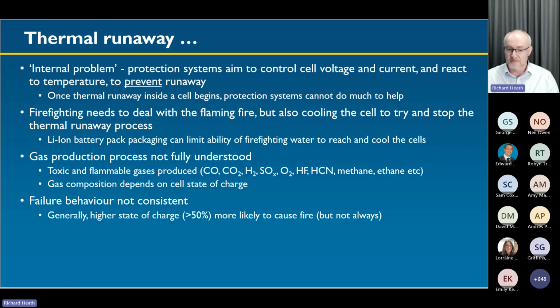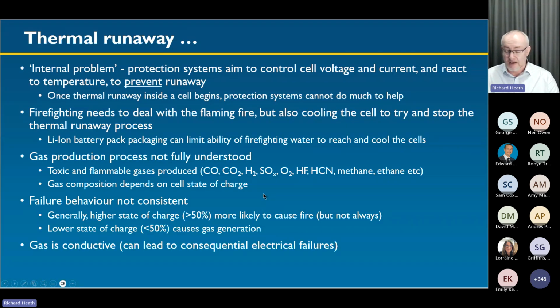Generally speaking, cells that are at a higher state of charge are more likely to cause a fire, those above sort of 50% or more, but not always. And those in a lower state of charge generally just generate gas, but it's quite a lot of it. And the gas is also conductive. So this can lead to consequential electrical failures if you have a cell that fails inside a piece of operating equipment.